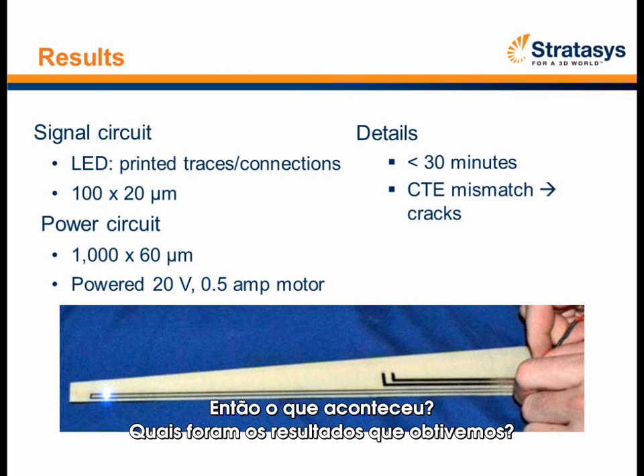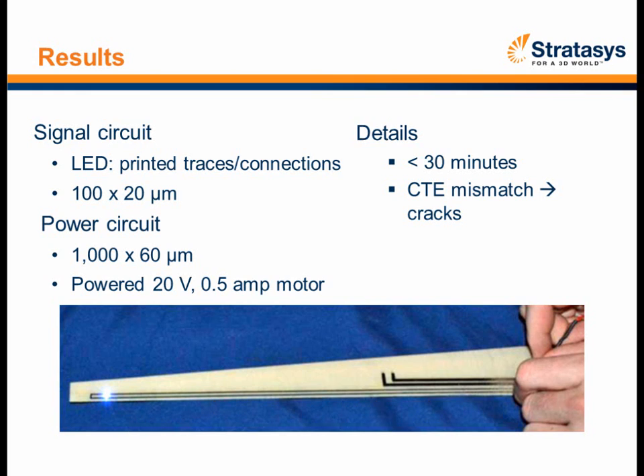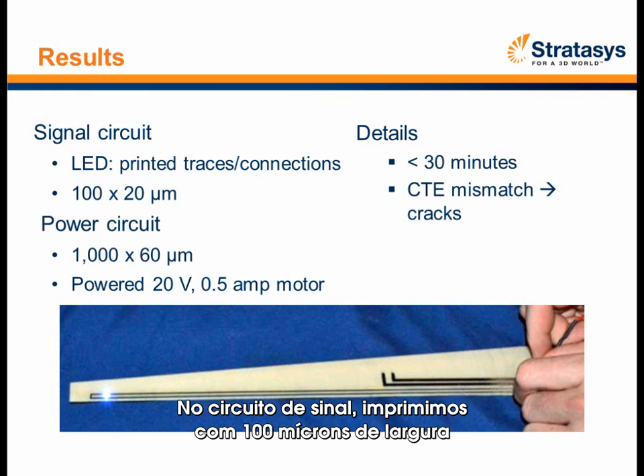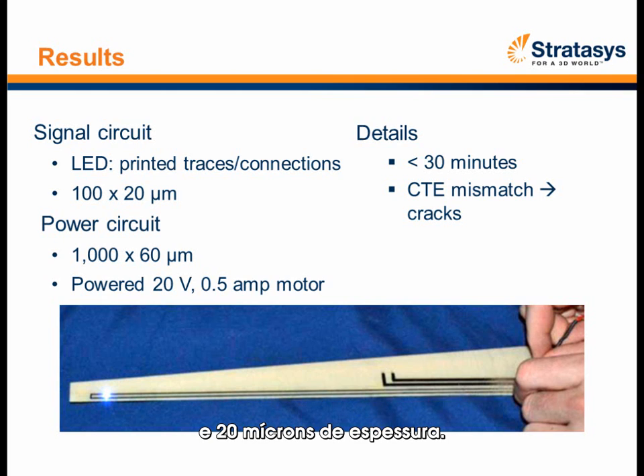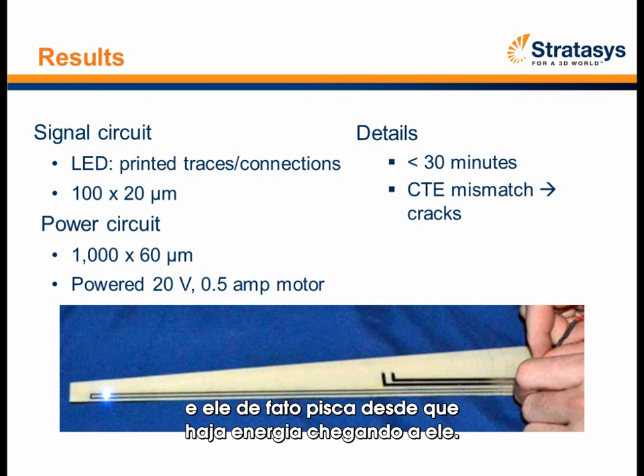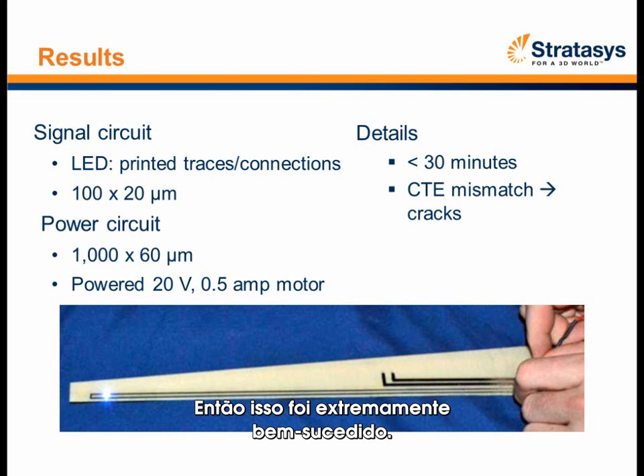What were the results that we came out with? So on the signal circuit, we printed those at 100 microns wide by 20 microns thick, and printed the traces right up onto the LED. And you can see right there that the LED is glowing and actually flashes as long as you drive power to it. So that was extremely successful. We're very happy with that.